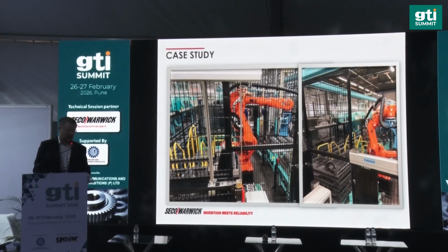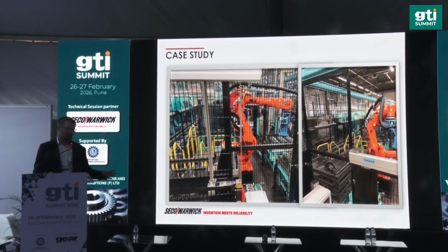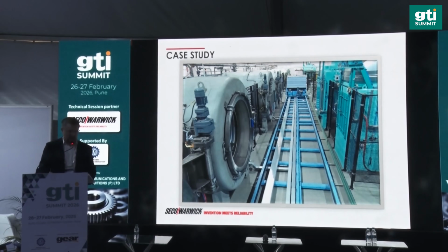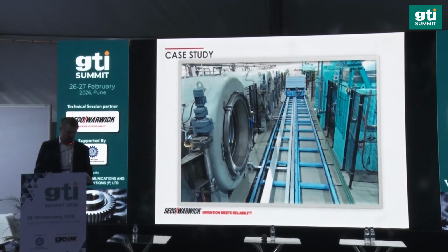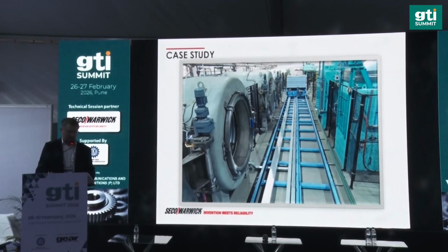The line was fully automated. The robots prepare the batches, including the fixture. That was quite unique because one operator is able to maintain the whole line. The whole line is equipped with 5 nitriding furnaces, 5 FNC furnaces, 2 preheating furnaces, a washing machine, and 2 cooling stations. And the heart of the installation is the loader, which connects all these parts for the whole cycle.